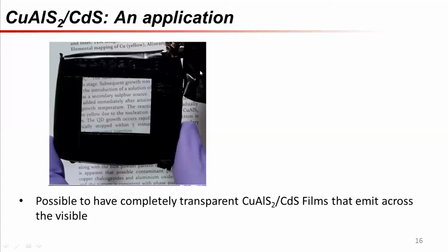To give another example of it not always working, the idea for zinc sulfide would be that if you look at copper iron sulfide, it's actually not possible to grow zinc sulfide cleanly on copper iron sulfide. Most of the time you don't get it. So those are tricks to be figured out. But yeah, it's definitely a good candidate material.